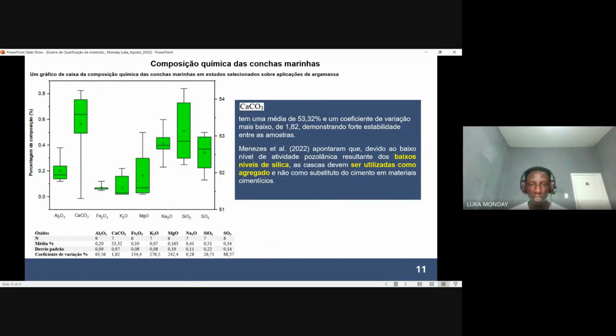While on the aspect of seashell, studies have clearly shown that the vast majority of the properties of seashell is composed of calcium carbonate. From the statistical analysis, an average of about 53.32% was obtained, which clearly shows that the vast majority of the chemical composition in seashell is calcium carbonate, with other materials having the least proportion.